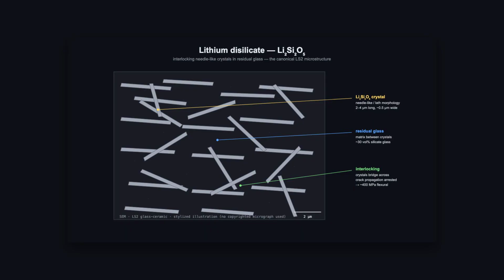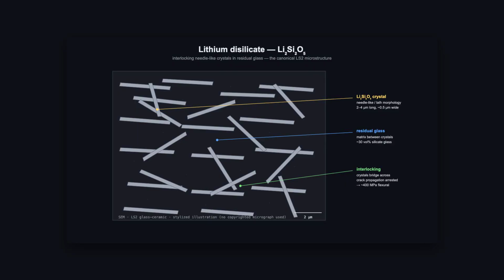Below the glass transition, below the temperature where atoms are supposed to move. Vickers hardness, 6.8 gigapascals. Fracture toughness, 1.5 MPa root meter. Indistinguishable from the conventional product. The dental prosthesis market in 2024 is worth $7.55 billion a year. A faster way to crystallize a crown is not a small thing.